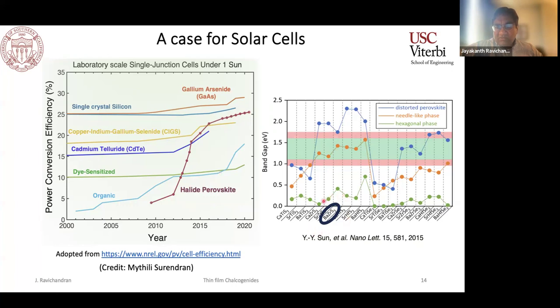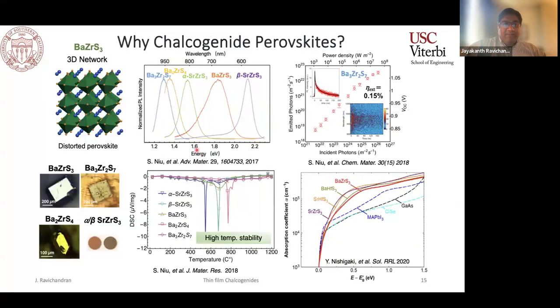So this is early work that was done by Shengbai Zhang's group at RPI, where he was able to predict some of the basic properties of these chalcogenide perovskites and highlighted potentially BaZrS3 as an interesting solar cell material. That led the community to look into these materials a little bit deeper. We spent a lot of time trying to grow some of these materials. We've shown that these materials can luminesce over a fairly broad energy range that ties nicely with the solar-optimal single junction energies. We also showed that they seem to have fairly attractive optoelectronic properties, very good thermal stability.